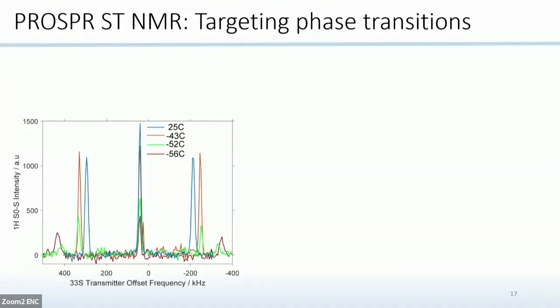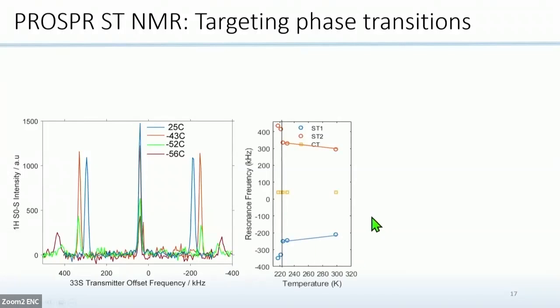And then when we cooled the sample further, we saw that the ferroelectric phase was formed. So then if we plotted in a similar way to the previous slide, we saw that there's, again, in a similar fashion, a gradual change in the CQ that we see from the satellites, and then an abrupt change below the phase transition, which is marked here by the black line.